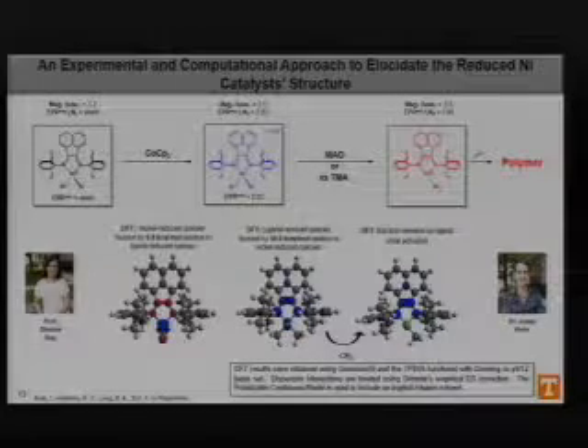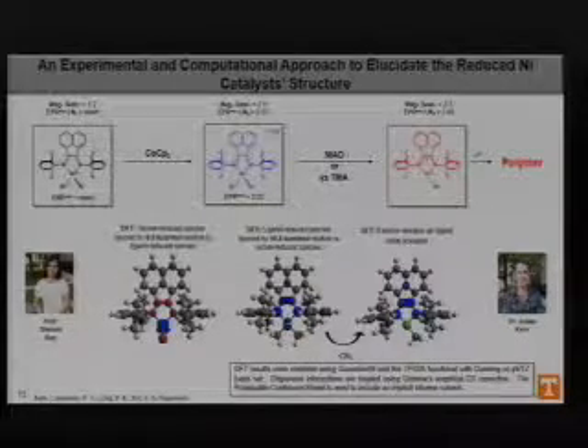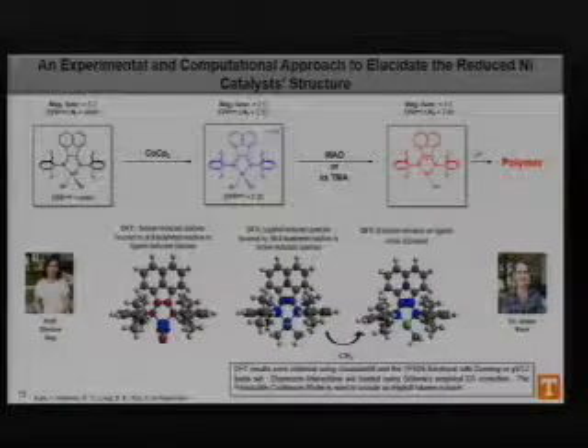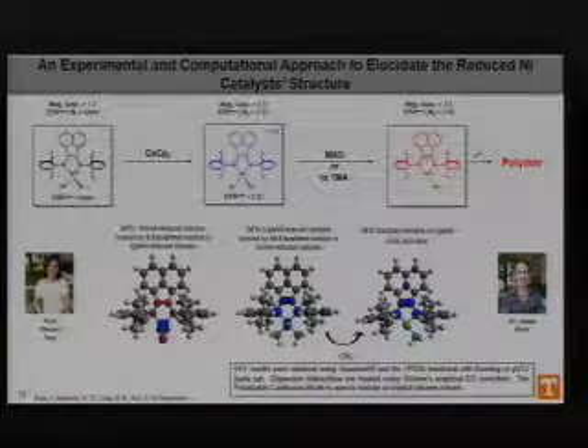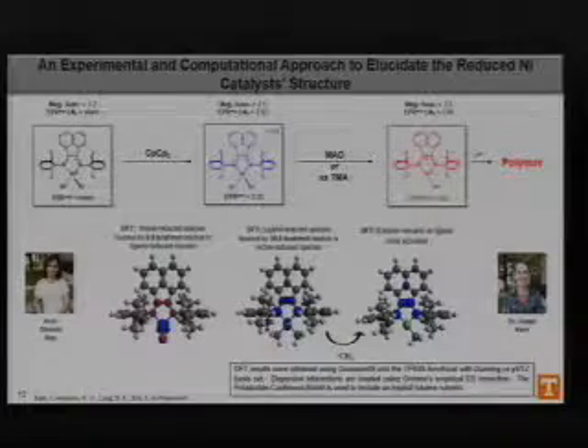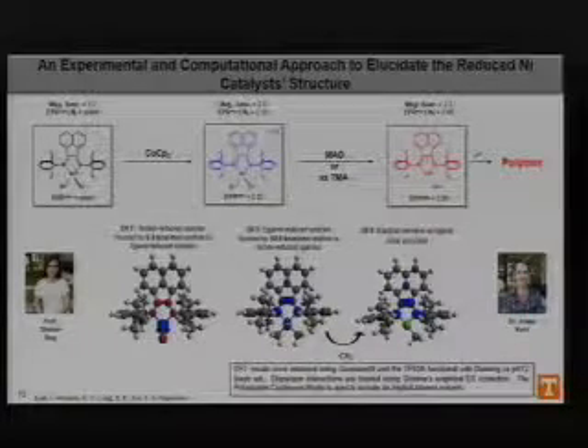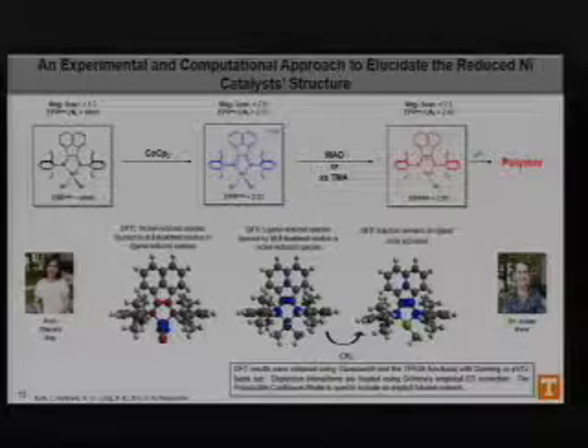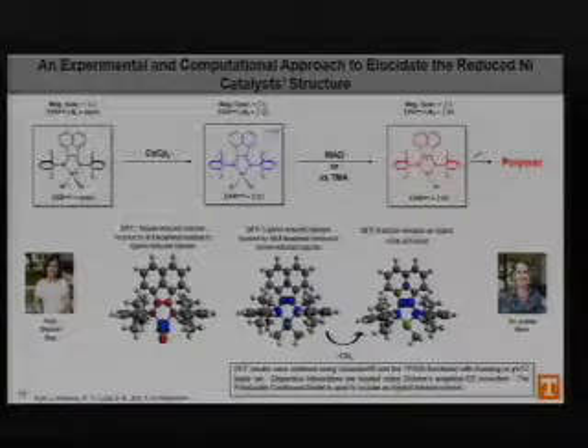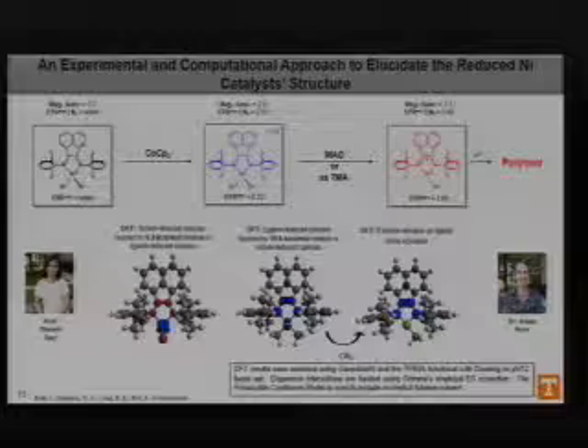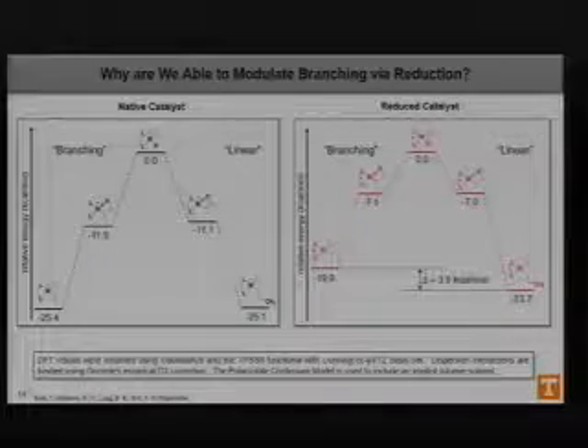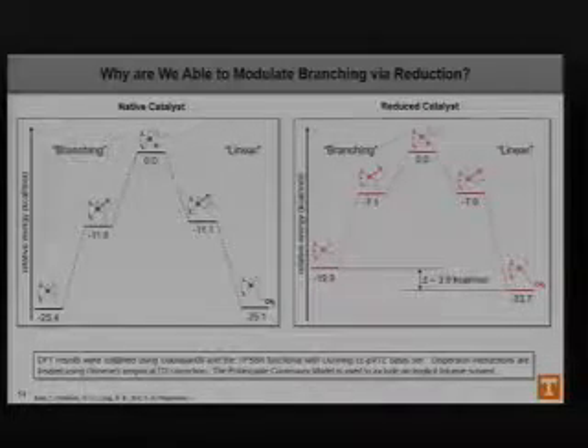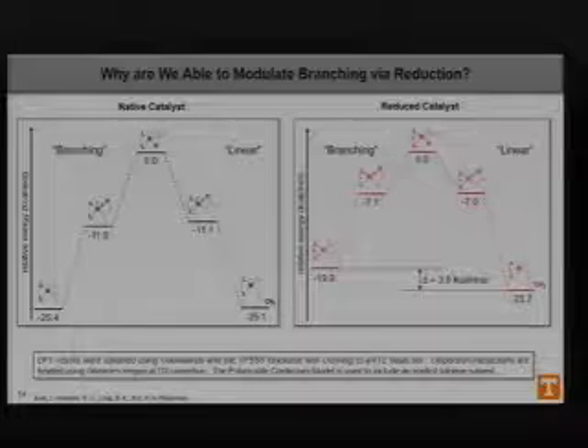So once we add MAO or TMA to the system, we found that it in fact did shift to the backbone, and this was favored in the DFT calculations, as well as from the experimental EPR, which agreed with the calculated EPR as well. The EPR of 2.00 represents an organic-based radical as opposed to the nickel(I)-based radical. So next, we needed to figure out why this worked and why this modulated branching.